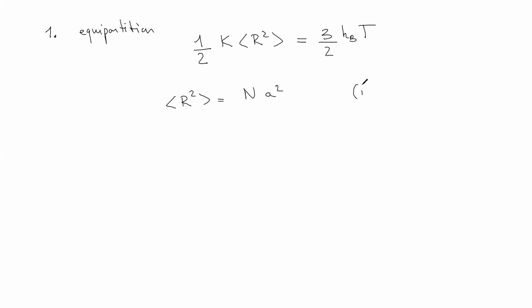So again, we are not discussing ideal versus non-ideal behaviors, because there are dedicated studies for that in the past tutorials. Here we want really to show the zeroth order effect. Then you can refine this picture at will. All right, so it provides immediately the fact that K should be equal to 3kBT over N a squared, which is something we already obtained.